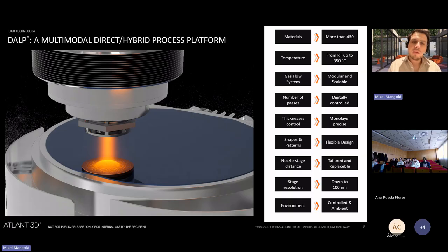Right now, we can deposit from room temperature to 350 degrees. We have obviously a gas flow. We can basically fully control the way the nozzle works. So we developed a software that can completely program what the nozzle does. And we have an optical system to measure that. We can fully control the thickness. We can fully control the shapes and the patterns, and we can control the distance, of course, from the surface.